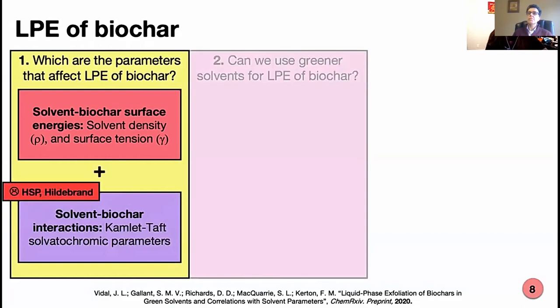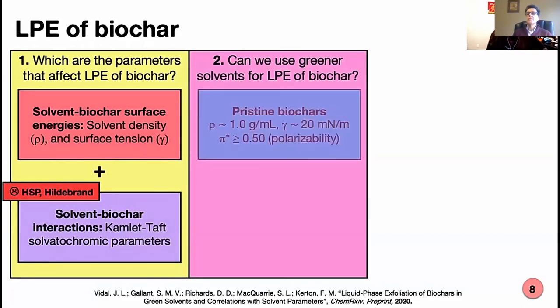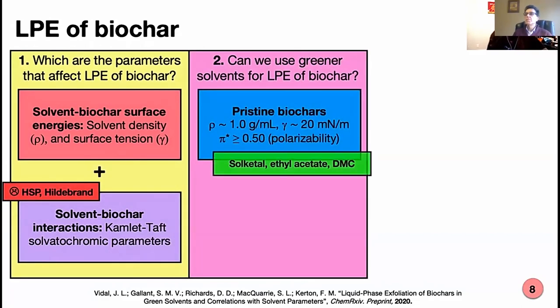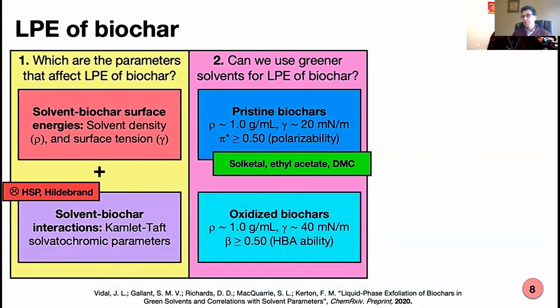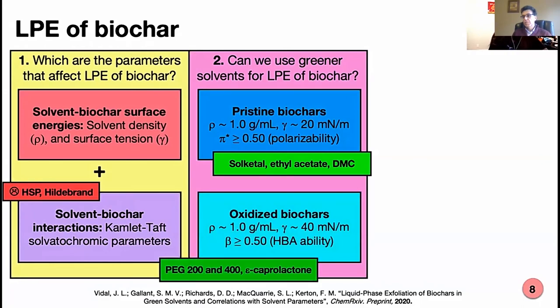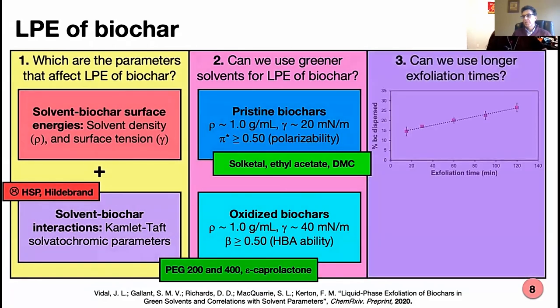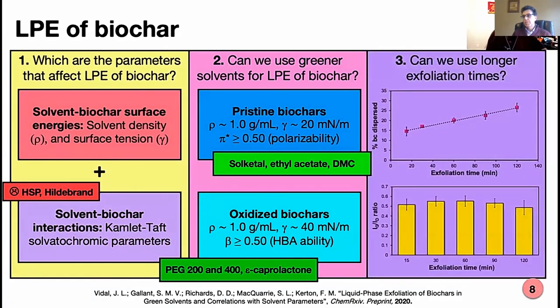It could produce biochar sheets with 15 nanometers thickness in solvents such as solketal, ethyl acetate, and also dimethyl carbonate, whereas oxidized biochar could be exfoliated in solvents such as glycol and caprolactone. And we also could exfoliate samples for at least 2 hours without any loss.